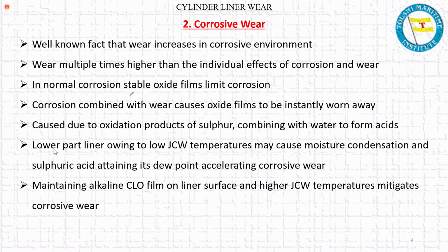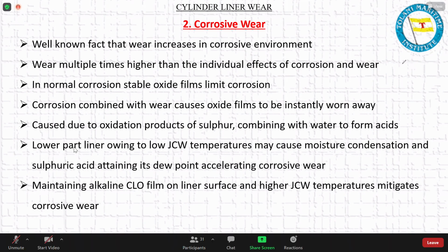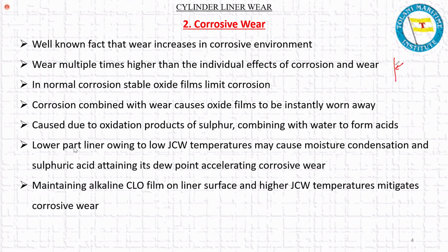But when you have the corrosive environment present, corrosion will first take place. First, the corrosion of the liner takes place. After the corrosion takes place, a stable oxide film is formed on the surface, chromium oxide or some oxide film. And further corrosion is not supposed to take place. It's supposed to stop at that point of time. But what happens? There is somebody known as the piston ring who is continuously rubbing onto the surface of the liner, and it is trying to rub out this freshly formed oxide layer, which is a very thin, nanometric or micrometric oxide film formed on the surface. It tends to remove that because of friction. As soon as that layer is removed, again the liner gets exposed to the corrosive environment, and again a stable oxide layer will be formed. By that time, the piston ring again comes up and removes this. So this is a chain effect, a cascading effect.